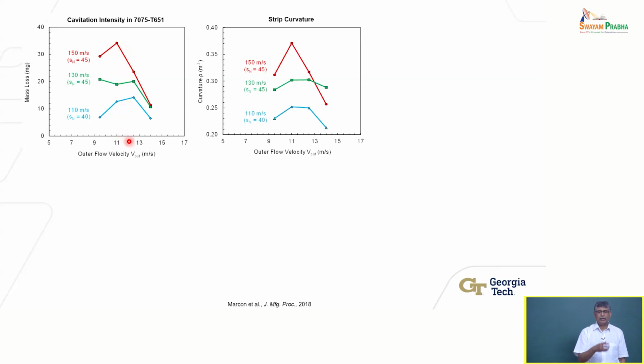And you can see here that, at 150 meters per second, clearly there's an optimum from these trends. Not every combination gives you the best result, but generally what we can see is that 150 meters per second inner jet velocity and 11 meters per second outer jet velocity combination gives me more or less the highest with our system. So, okay, now how do I quickly test without having to do residual stress measurements using X-ray diffraction? How can I tell that under these conditions I will generate more or less residual stress?